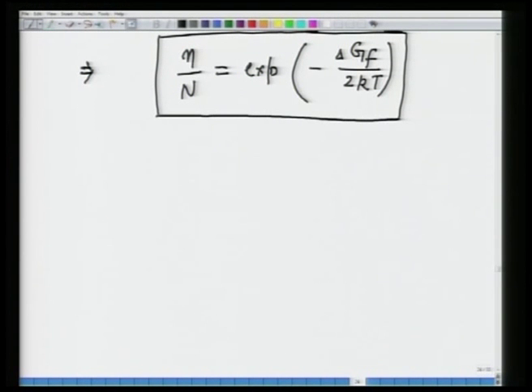So, watch this, what this tells you is that the formation of vacancies is an exponential function of energy expense per pair and temperature. As you can see now here, as the temperature increases, this number will increase, and as this number increases, this number will decrease. It is going to be much harder to form defects when you have low temperature and higher energy expense. Now, this delta G f can further be broken into delta H f minus T delta S